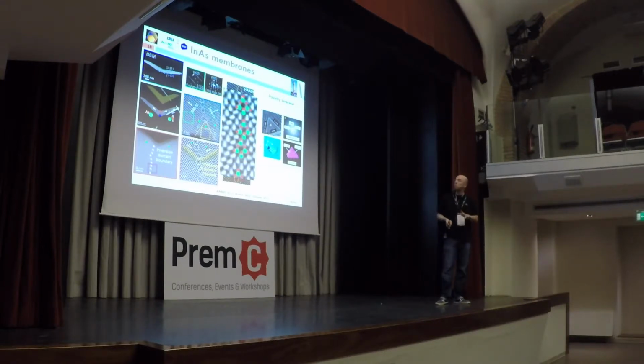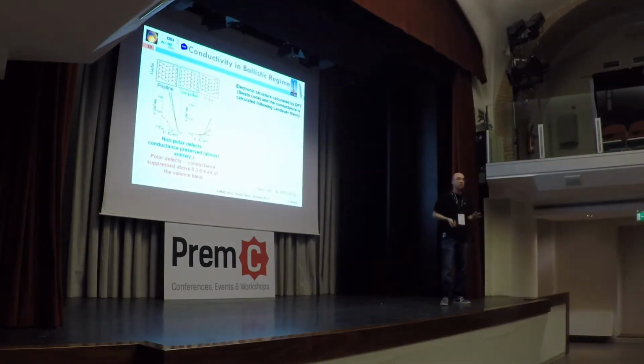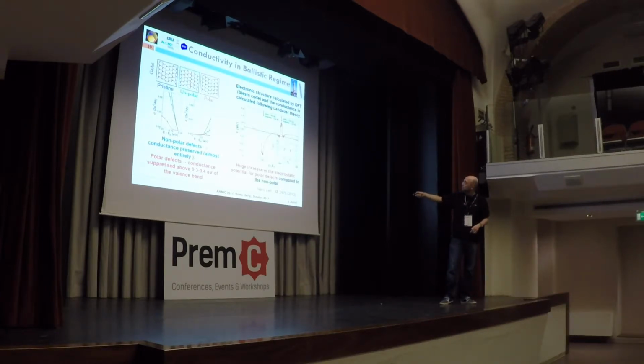But then, first of all, we need to simulate what is going on here. Imagine that there is no interface, without a boundary. Imagine there is an interface without a change of polarity. And imagine that we have, that is the case, an inversion polarity boundary. In the case of an inversion polarity boundary, what we have is a perfect suppression of the conductance of our carriers. And this is why some potential barriers, electrostatic potential barriers, are created exactly at the position of these inversion domains.